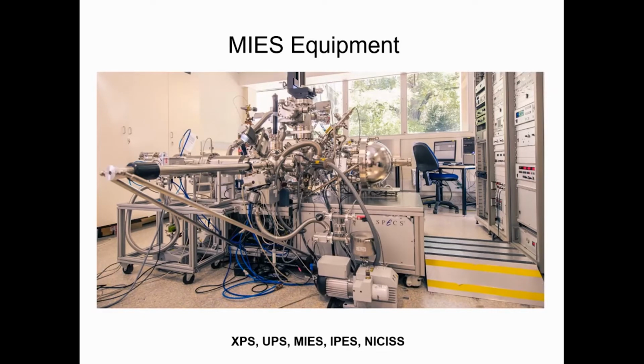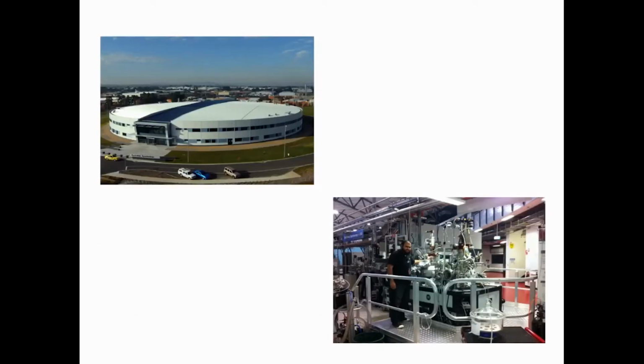Because we have very small nanoclusters, sometimes the intensity of the peak in XPS is not that high. That's why we move to synchrotron XPS. Synchrotron XPS provides huge radiation intensity, where we can narrow the energy gap and get a huge intensity to show us this amount, because we deposit a very small amount to avoid aggregation of the nanoclusters.